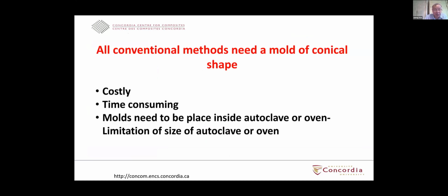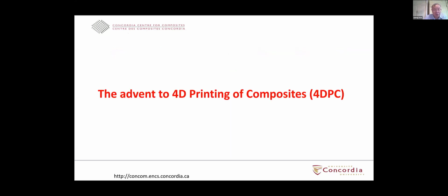So that means that in the case of the conventional methods that exist right now to make the shape of a cone, they have something in common. They always have a mold. You always need to have a mold to do that. And when you make a mold, it is costly, it is time consuming. And also, when you do something using carbon epoxy, you need to cure it. That means you need to put that inside either an autoclave or an oven to heat up the resin to cure. But if you want to make a large structure, then there is a limitation in the size of the autoclave or the oven. So basically that is the so-called state of the art, the way people make the conical shape.